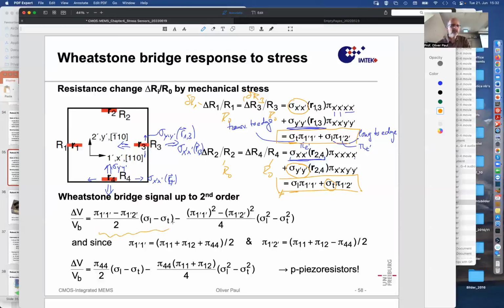Yeah? So sigma L minus sigma T is the factor to which delta V over VB is proportional. And that is the difference between the thick arrows minus the thin arrows. And they are not the same. I mean, the longitudinal stress, sigma L here, and here is sigma transverse. Sigma L is about Poisson's ratio times sigma transverse. So there is a factor. This is only 0.07 of sigma transverse, and so it's almost as large as sigma transverse with a minus sign. And the rest of the Wheatstone bridge, this plus minus up here, just produces this combination of pi coefficients as a prefactor in front, with a factor of 2 remaining.